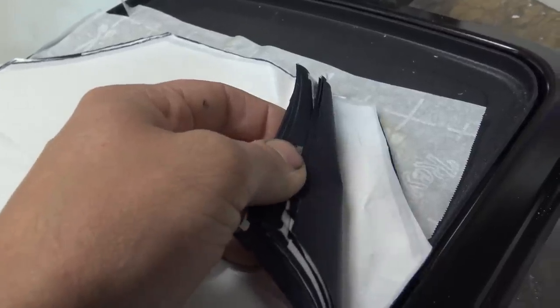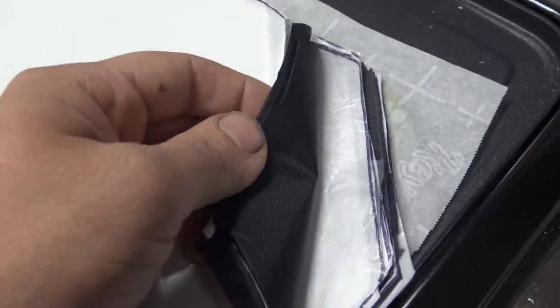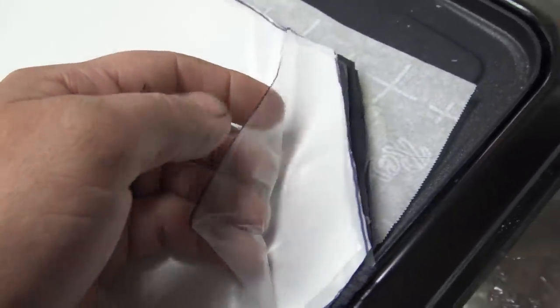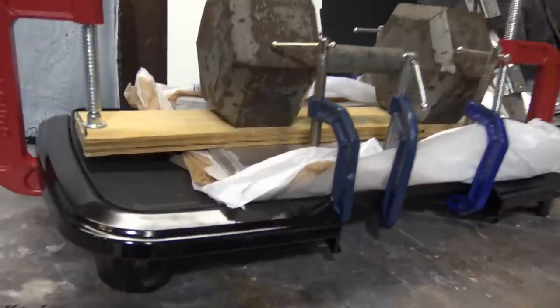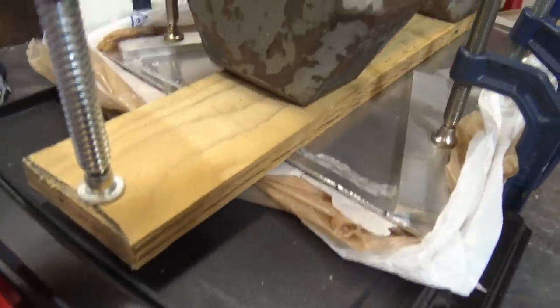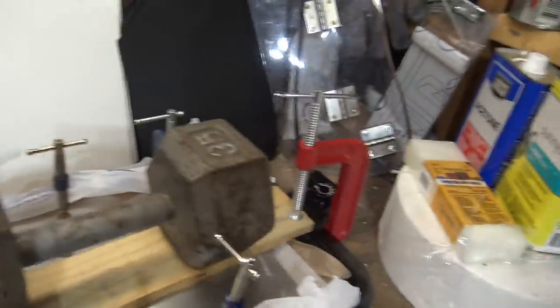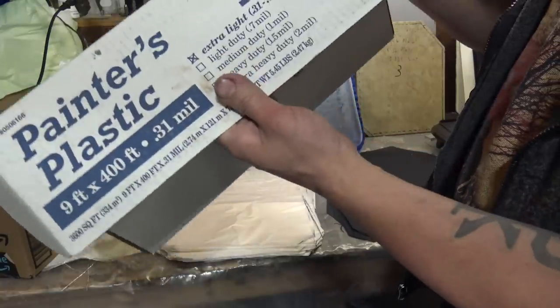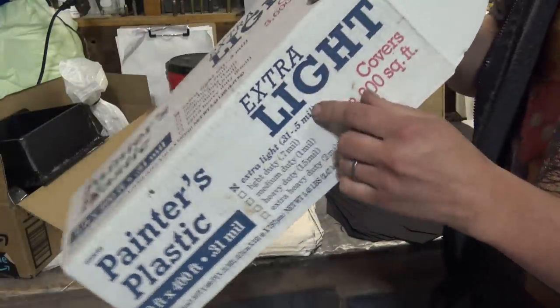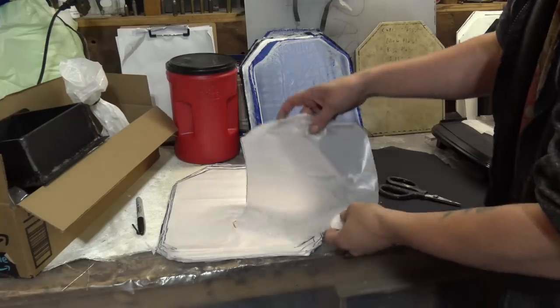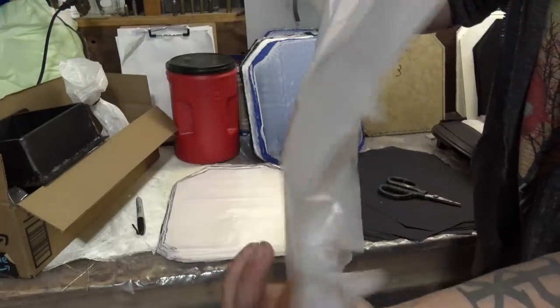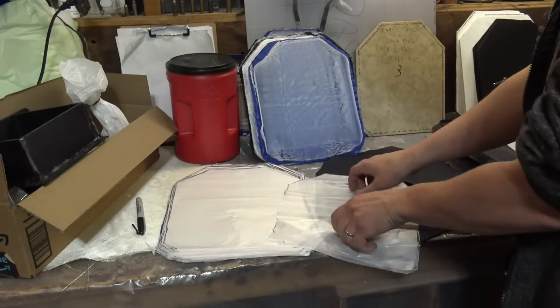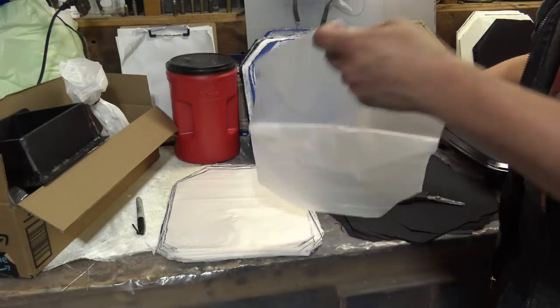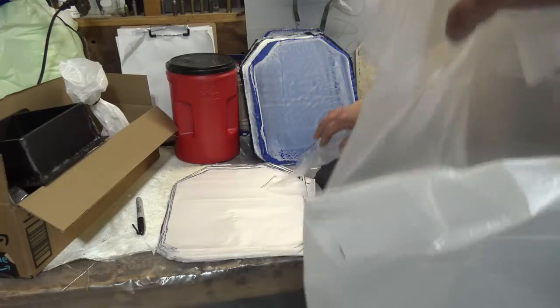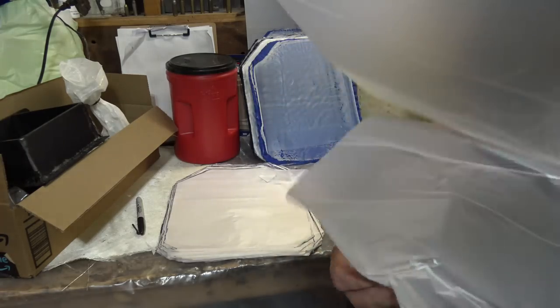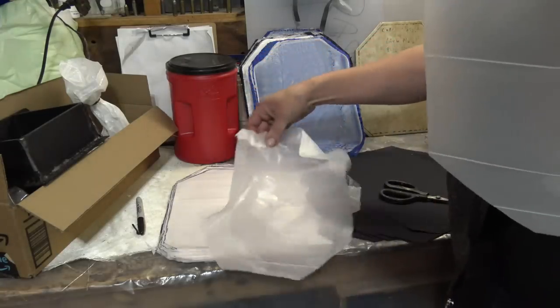So once I had this method down, I started doing 10 layers at a time instead of 5. I also added 2 larger clamps and upped the weight to 35 pounds on top. This helped even out the pressure on the top plate. I also upped the amount of HDPE in between the nylon from 2 layers of film up to 4 for both the grocery bag material and the painter's plastic. So essentially 2 grocery bags per layer of nylon. This made a much stiffer composite with less pits and holes in the plastic.